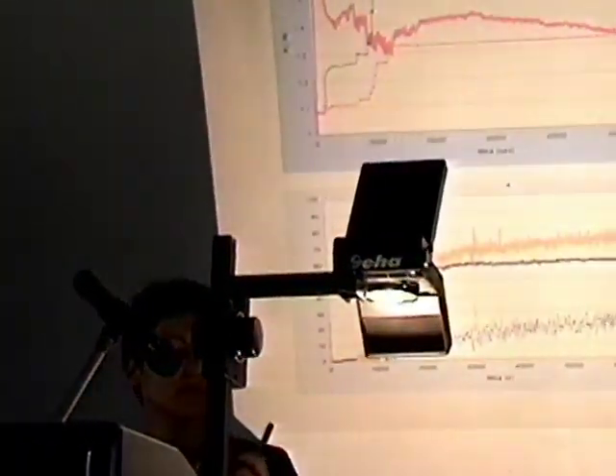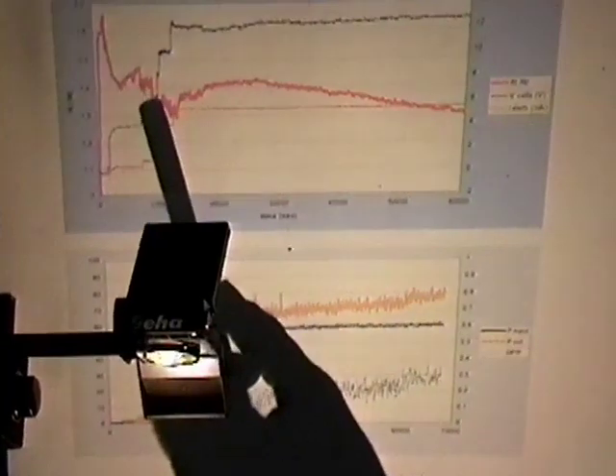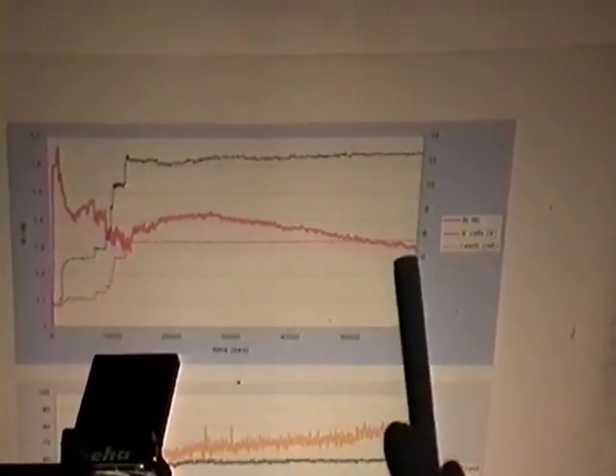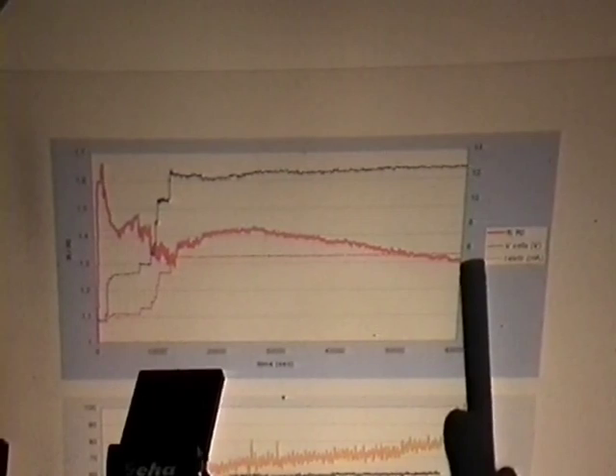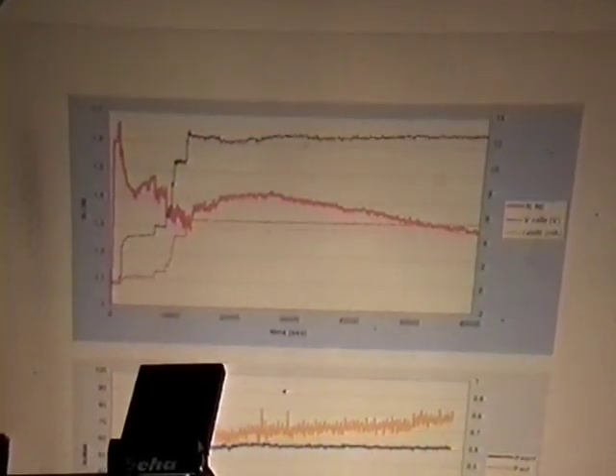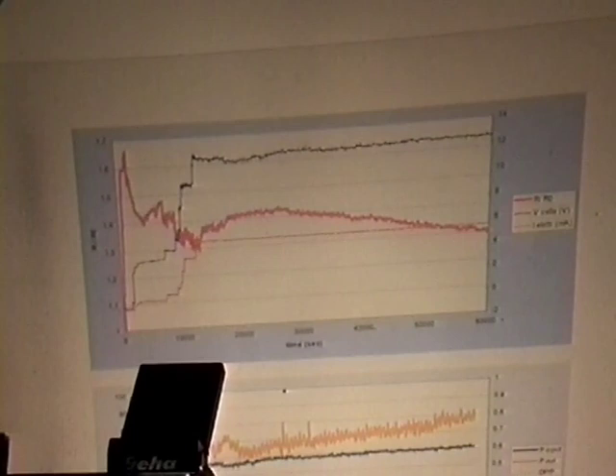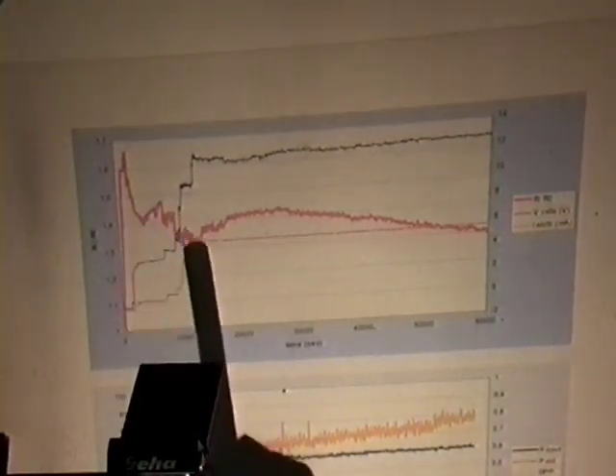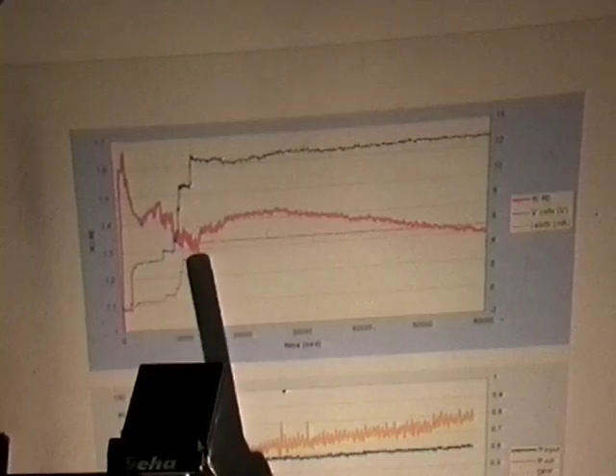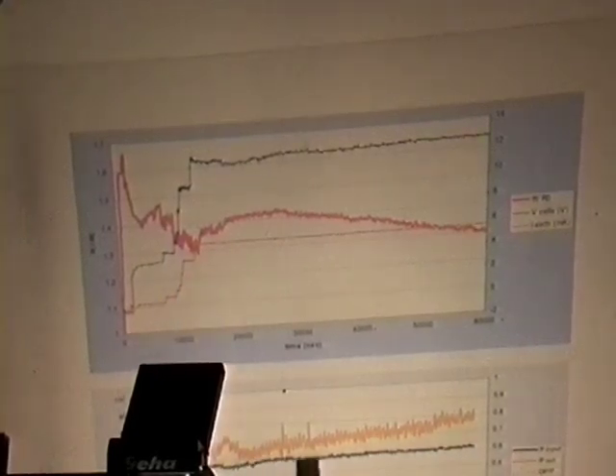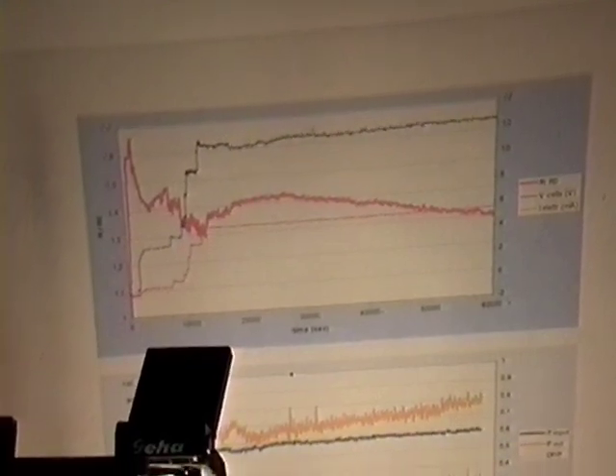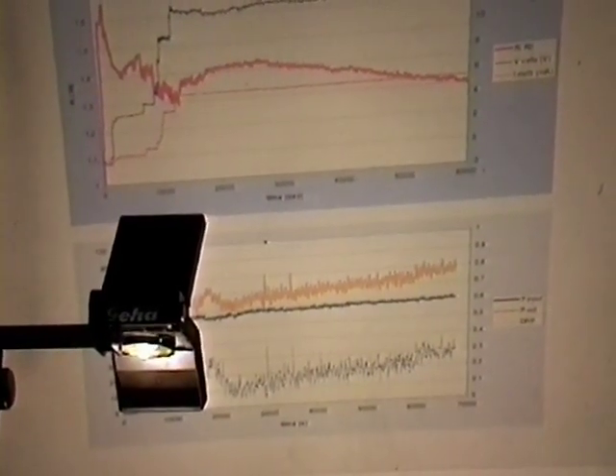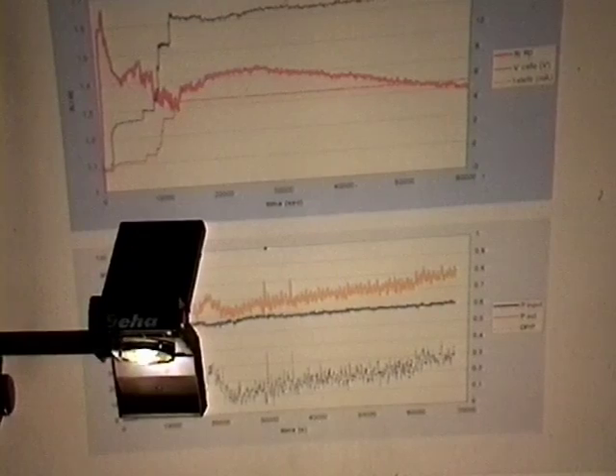This is an example of a typical experiment. In the first graph, you can see that this pink curve is the relative increase of the resistance, and the red curve is the output power compared to the input power. This is the percentage on the right scale. As you can see, as soon as the sample reaches high loading value, it starts the production of heat excess. And in this particular case, we have up to 30% of the input power. It's very clearly measured.